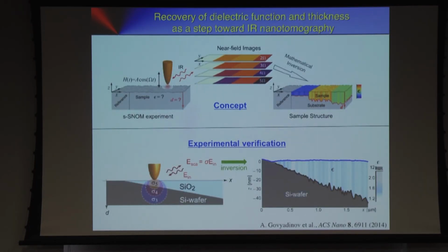Like in any tomography, if we scan, we get a kind of a projection. So we need independent multiple images of the sample. In tomography, normally you take your sample, you get different projections, you make back projection via Radon transform or whatever. But this is all linear. In our case, everything is nonlinear, and that makes it extremely challenging. The other question is, we need different projections. We cannot rotate the sample here.